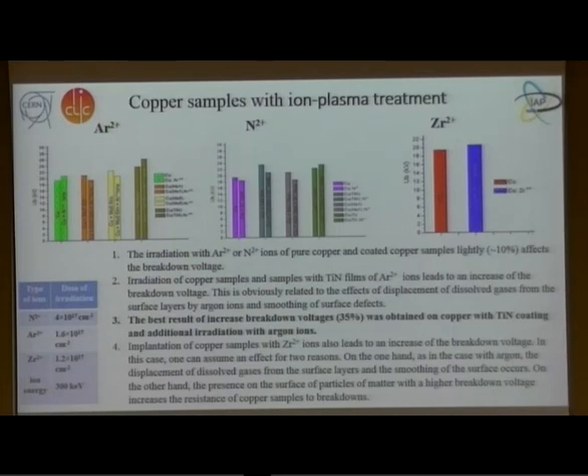This is related to the effects of displacement of dissolved gas from the surface layer by argon ions and smoothing of surface defects. The best result, an increase in breakdown voltage of approximately 35%, was obtained on copper with titanium nitride coating and additional irradiation with argon ions.